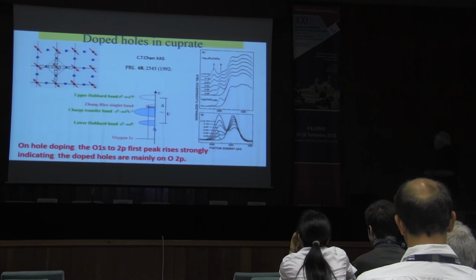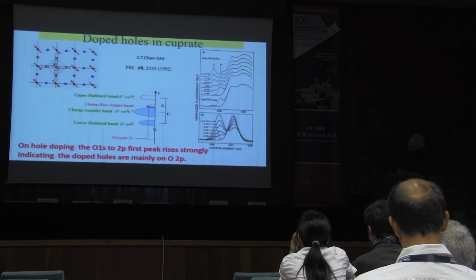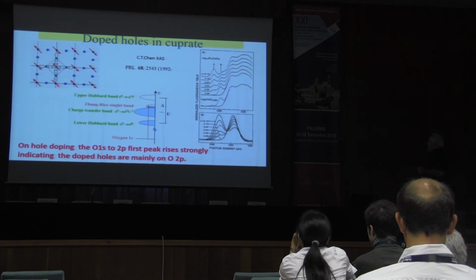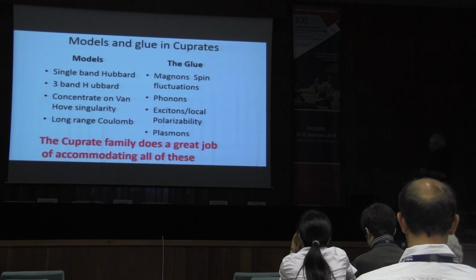We know from X-ray absorption spectroscopy, so this is a picture of the cuprates. I think you've all seen it very many times, probably, where you have a spin of a half, copper is d9, you have a spin of a half on each copper, they're antiferromagnetically ordered, and now we're looking at, for example, a hole on the oxygen. And how do I know the hole is on the oxygen mainly if I dope the system? Well, X-ray absorption spectroscopy shows me in this system La2-xSrxCuO4, that if I had just La2CuO4, the copper would be 2+, would be d9, and now I replace lanthanum with strontium, and I would get some copper 3+.